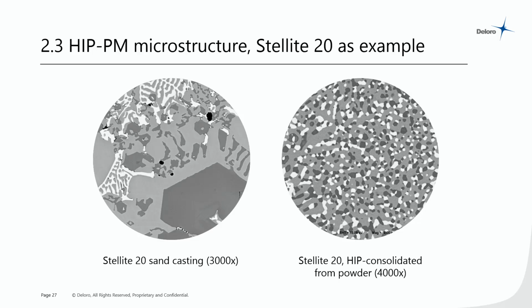However, if you take exactly the same alloy in powder form and you HIP that powder, you get a completely different microstructure. The carbides are homogeneous, they're rounded, they're small. So a crack cannot travel through this microstructure as easily. It is much tougher.